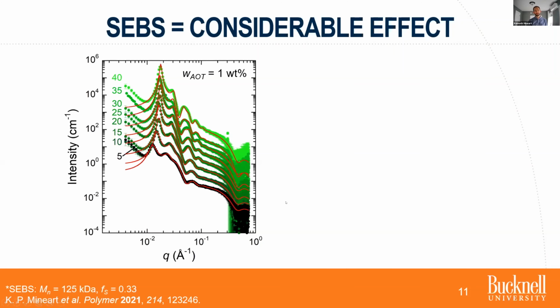And now I'll pause and take a second to talk through some of the features we're looking at here in terms of the copolymer assembly behavior. First, there's a sharp peak at lower Q, relatively speaking, which corresponds to the separation of the polystyrene domains, the physical crosslinks in our systems. And then second, there's a series of broader features in the mid-Q range, again relatively speaking, that correspond to the size of those crosslink domains.